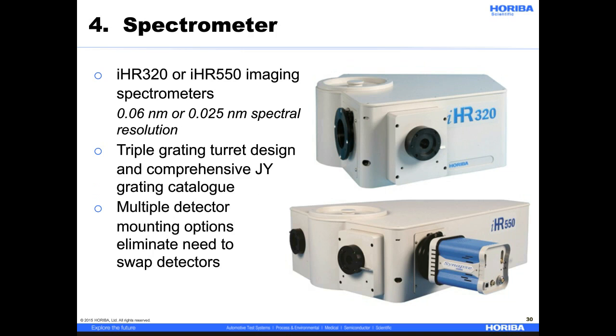While all the systems shown so far have been equipped with an iHR320, there are multiple spectrometer options. The 320 mm focal length spectrometer gives a resolution of 0.06 nanometers, while the 550 mm focal length spectrometer gives a higher spectral resolution of 0.025 nanometers. Both spectrometers use a triple grating turret design, which allows for 3 gratings to be mounted at once with automated switching between them. Coupled with HORIBA's large grating catalog, the spectral range over which the spectrometers work extends well into the infrared. Finally, the spectrometer is equipped with 2 exit ports so that multiple detectors can be mounted without the need to swap between them when switching from one experiment to another.